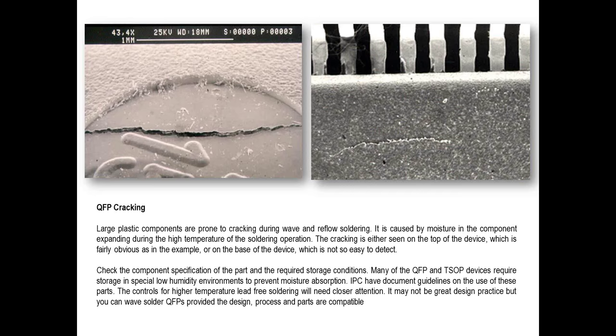Now, cracking of components, again, still happens with BGAs and plastic packages. Fortunately, with IPC controls, you shouldn't have this particular problem. But there are still times when design engineers select components that are not compatible with the peak temperature of a normal process, or components are bought inappropriately for a lead-free process. There's no excuse for this. It's down to the designers to make sure that we specify the correct components for a particular process.